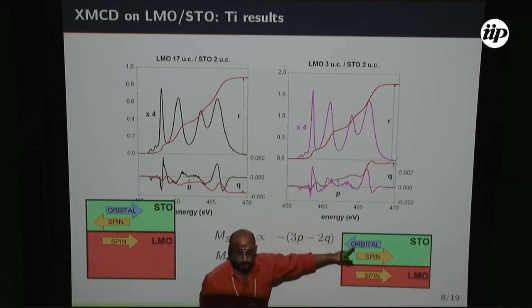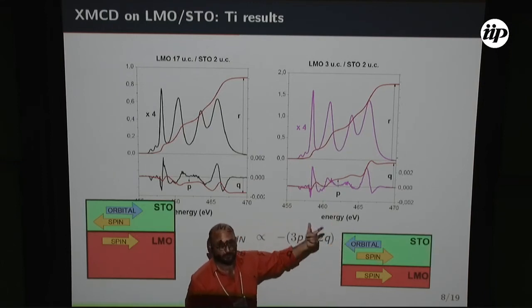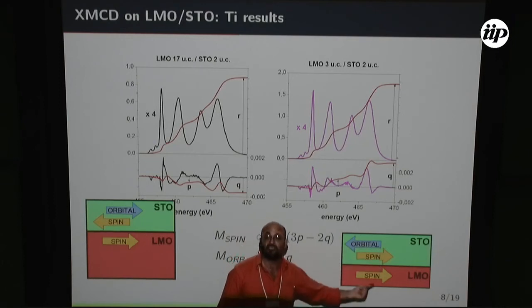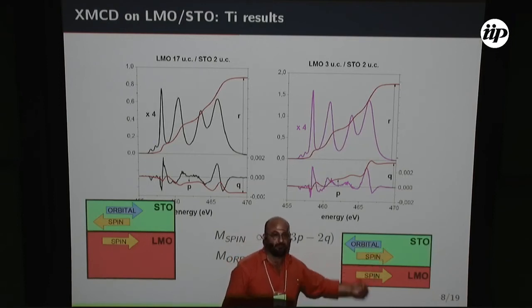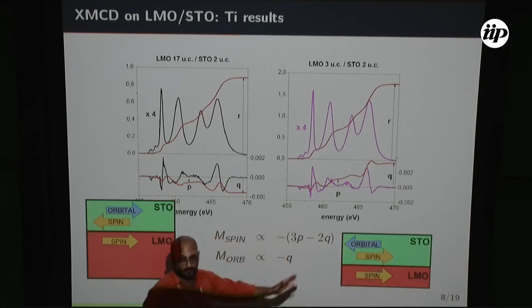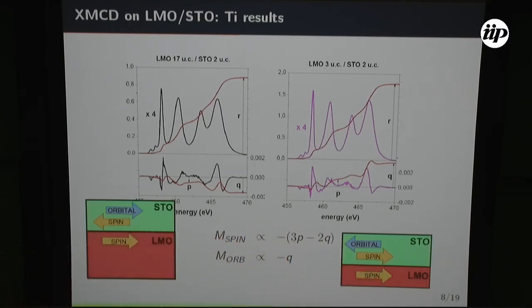Furthermore, this is strontium titanate, so it's d0. So you already know if there's a magnetic moment, there was some charge transfer here at the interface. So you need some electrons going to the titanate, and you can see this also from the spectrum. So with that, I would like to show you how powerful this technique can be to give detailed information about the interfaces. With this information and with the good enough Goodenough-Kanamori-Anderson rules, you can make the complete scenario for this kind of material here, okay?